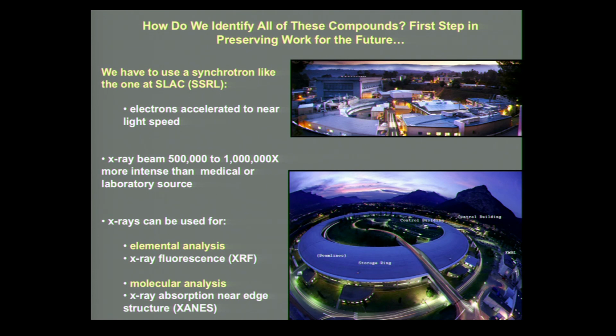So how would one go about identifying all of these compounds? Because that's really the first step in preserving these priceless works for the future. And it turns out that we have to use a synchrotron, just like the one here at SLAC. And inside a synchrotron, electrons are going to be accelerated to nearly the speed of light, and we're going to have very intense X-ray beams being given off tangentially to the ring containing the electrons. And when I say a very intense X-ray beam, I mean somewhere between 500,000 and 1,000,000 times more intense than the X-ray beam you would be exposed to, for example, if you had your arm X-rayed at the doctor's office.